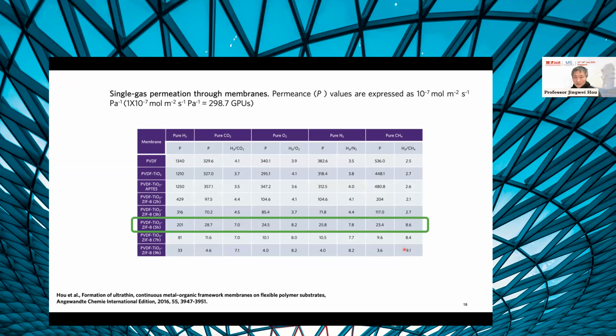But what I want to highlight is after a certain period of time of the crystal growth, we can achieve, at that time, we believe, pretty decent molecular sieving. So for the pure hydrogen, we can achieve around 201 for the permeance, and the selectivity against the CO2 is around 7, which is pretty good.